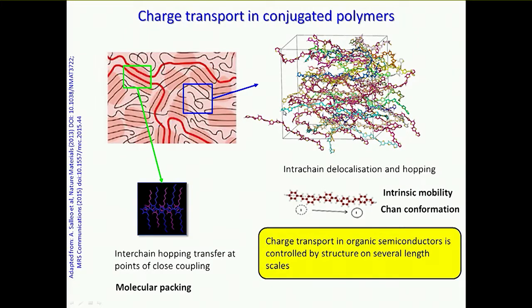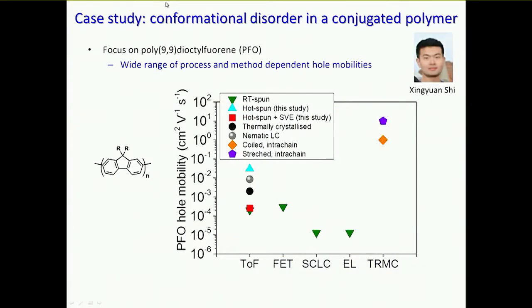Now, one of the problems with charge transport is that because every conjugated polymer has got a gigantic conformational phase space, you can effectively prepare the material in a wide range of different microstructures, and different microstructures will express different electronic properties. And to give you an idea of this, this is a simple conjugated polymer. We call it polyfluorene. And here on the right, and this is a logarithmic scale, there is a collection of reported hole mobilities for that conjugated polymer.